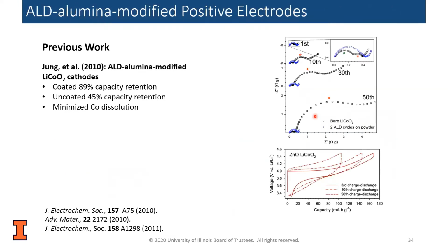In the first case, here is an example where some researchers modified the surface of the electrode, the positive electrode that is, with ALD alumina. And so they found that a coated sample had an 89% capacity retention as compared to the uncoated sample. And so they also noticed that there's a minimized cobalt dissolution in this case because of the coating.